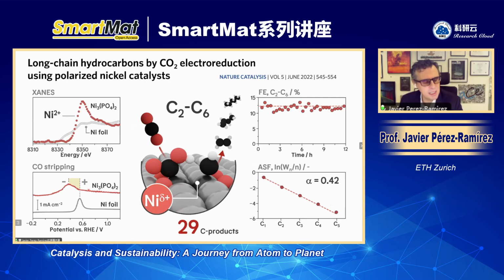And the idea behind the coupling ability of polarized nickel is that upon polarization, compared to metallic nickel, illustrated here by the nickel foil, there is a shift of the binding energy of CO to weaker values. And the weakening of the CO adsorption makes it possible for fragments to desorb and also provides the catalyst with the ability to couple the CO into long-chain hydrocarbons.